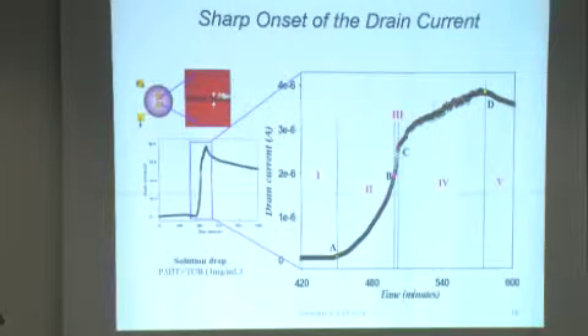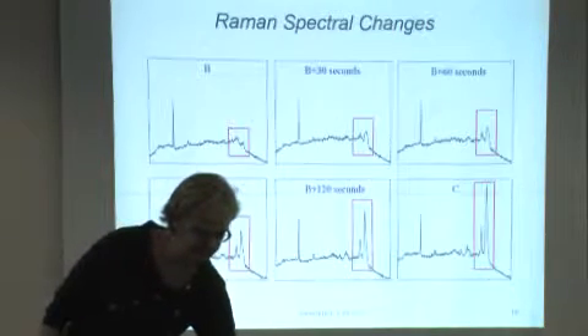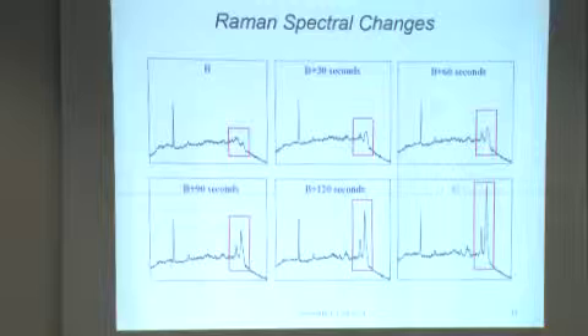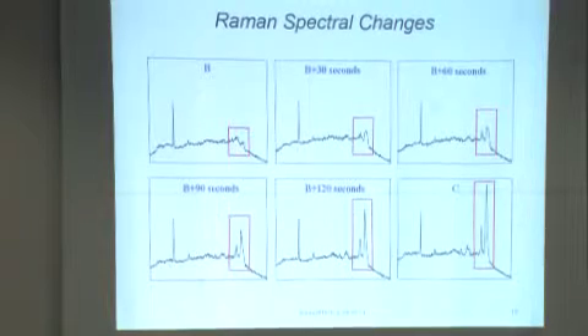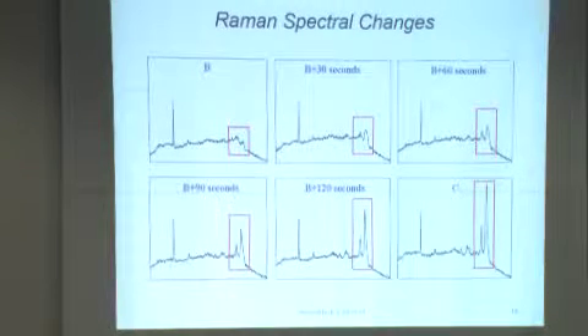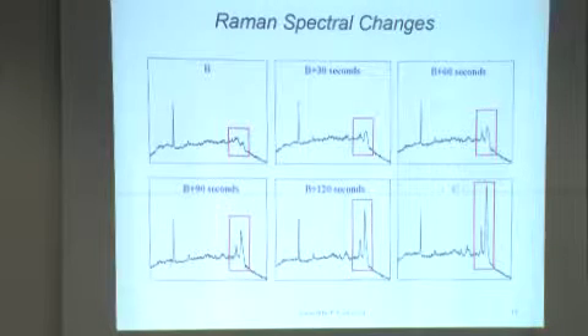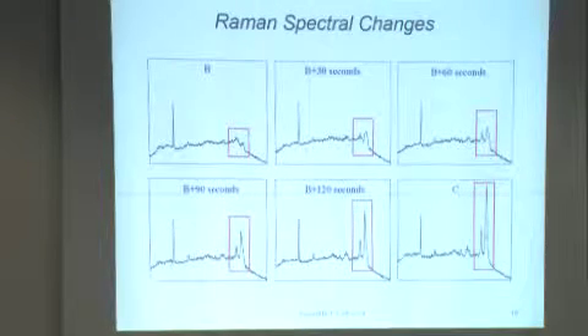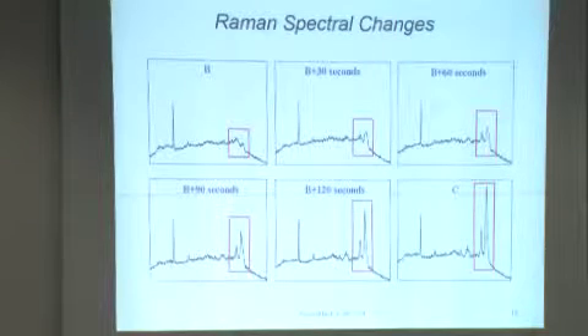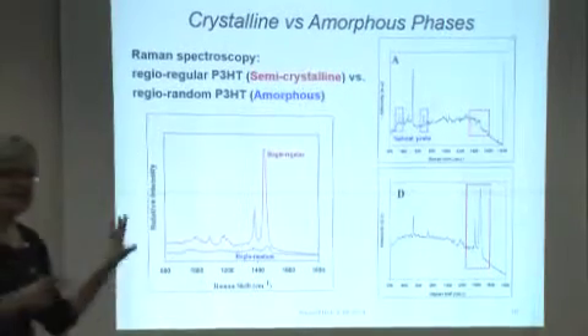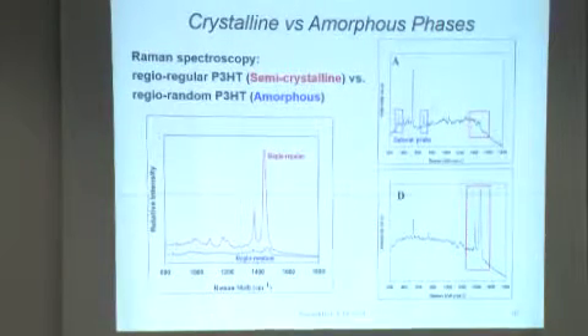So if we focus on this area, it's only about 2 minutes that we go from what looks like an amorphous blob in the spectrum to having very sharp absorption bands that are associated with crystalline poly-3-hexylthiophene. All right, so in this short time frame of solvent evaporation, we're seeing substantial changes in the material itself. And that's at a point where we still have a little bit of solvent present